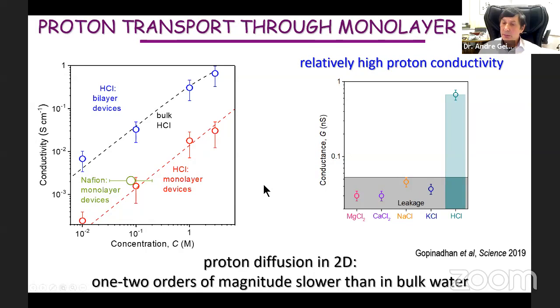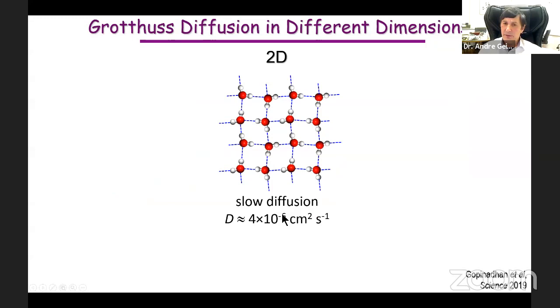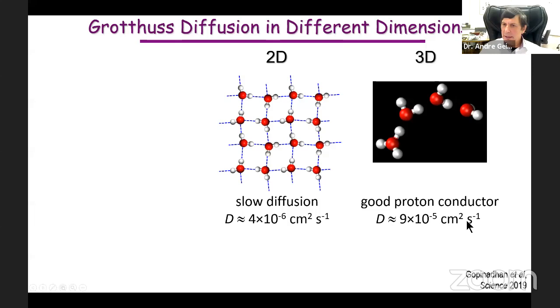So the diffusion coefficient is 10⁻⁶. And this is what we believe is how water in monolayers looks like. It's kind of an icy arrangement, a very well coordinated arrangement. If you compare this diffusion with diffusion in bulk water, it's an order of magnitude, about 20 times slower than in bulk water.